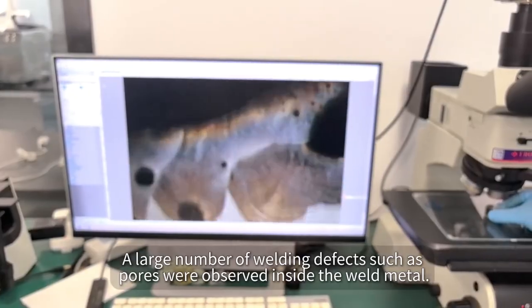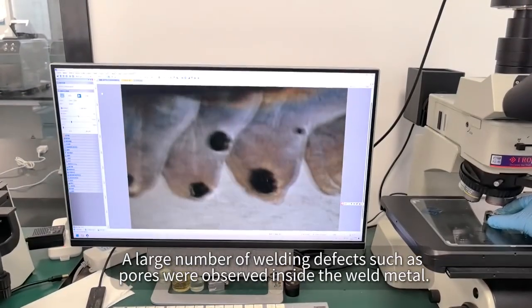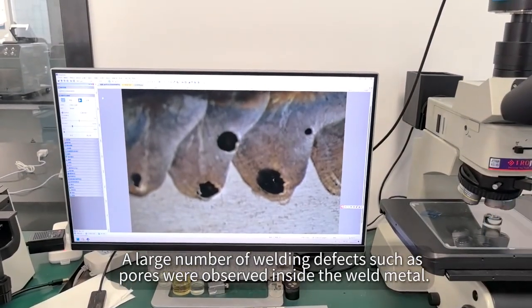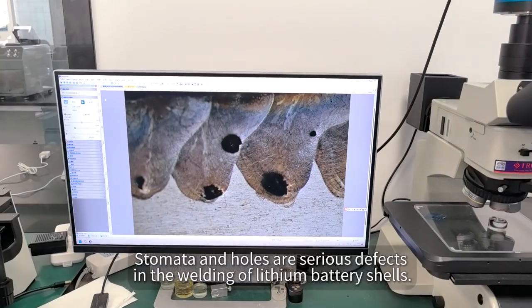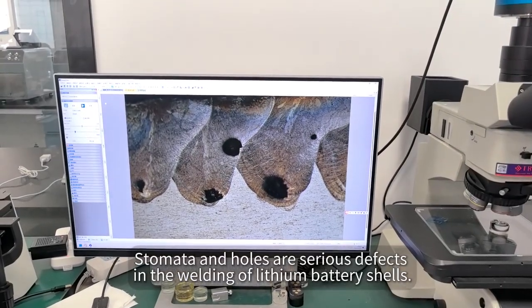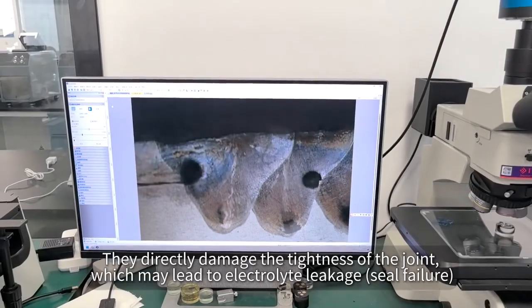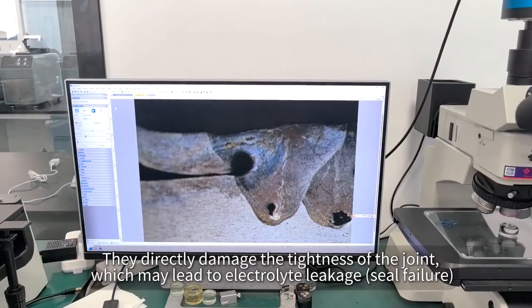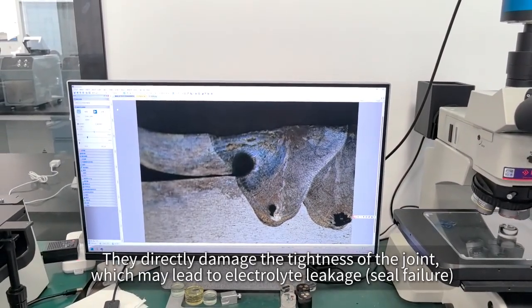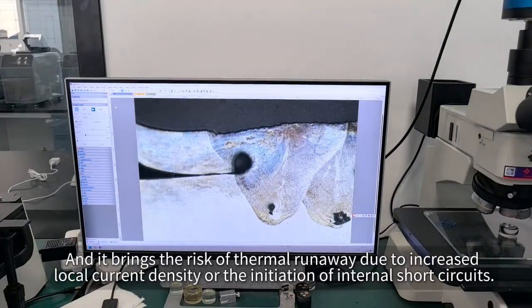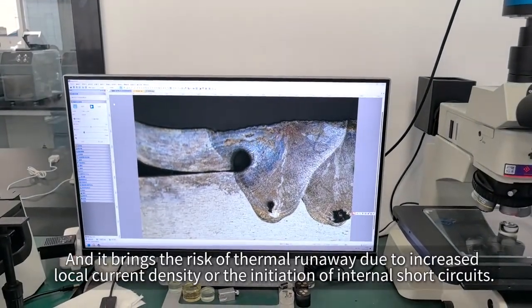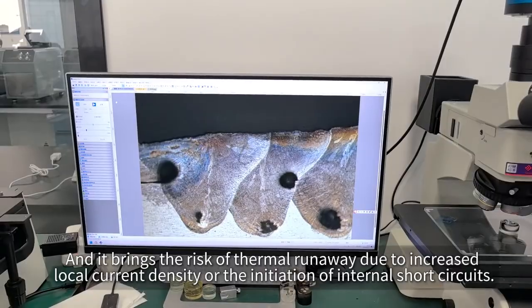A large number of welding defects, such as pores, were observed inside the weld metal. Pores and holes are serious defects in the welding of lithium battery shells. They directly damage the tightness of the joint, which may lead to electrolyte leakage and seal failure, and it brings the risk of thermal runaway due to increased local current density or the initiation of internal short circuits.